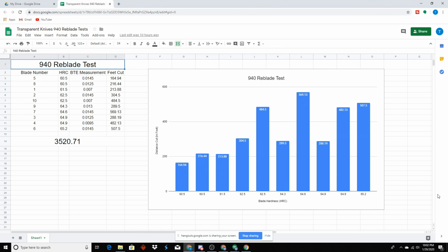You know what I mean? And to some extent, it's true for production companies, I think, because most production companies, except Lion Steel, do the same protocol or they attempt the same protocol. So, to the extent that different blades get quenched at different times and there's slightly different soak times and hot and cold spots in the oven, there's going to be slightly lower HRCs, and those lower HRCs are going to perform worse because of the reason why they're low, right? The reason why the 64.6 is lower than the 65.2 is not because I did something wrong, like I left it in the oven too long or forgot to quench it quickly. It's because of a completely different protocol idea, right?